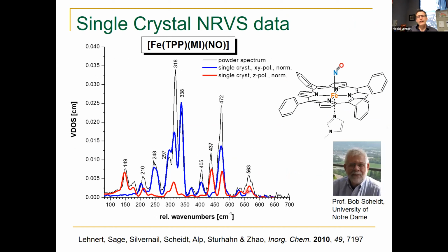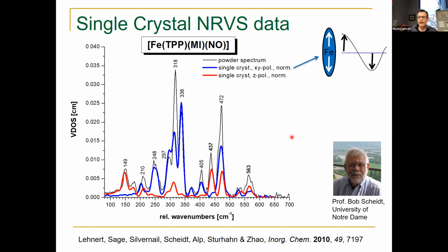is actually doing single crystal nuclear resonance vibrational spectroscopy, which was really pioneered by Bob Scheidt and Tim Sage. And here are the data then again for our target complex, right? Where in blue, we have the data now where we have a single crystal, so all molecules, right, have the same orientation. We orient the crystal in a way that now here is the beam with the linear polarization, and now we orient the heme in parallel to the directional polarization. And so now we only get scattering from vibrations where the ion moves in the plane of the heme. So we get in-plane intensity, which is that spectrum here shown in blue. And then rotating the crystal, we get the out-of-plane intensity.